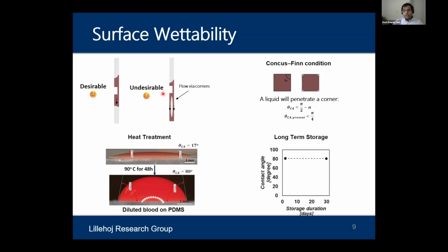So when we keep a fabricated chip at an elevated temperature, the contact angle recovery is very fast. Fast in the sense it is in days instead of weeks. So we kept the device at 90 degrees Celsius for 48 hours. And in this image, you could see that just after PDMS is treated with the plasma, the diluted blood makes a very acute angle, 17 degrees. And after the recovery of the contact angle, after 48 hours of heat treatment, it recovers the hydrophobicity which the PDMS is supposed to possess.